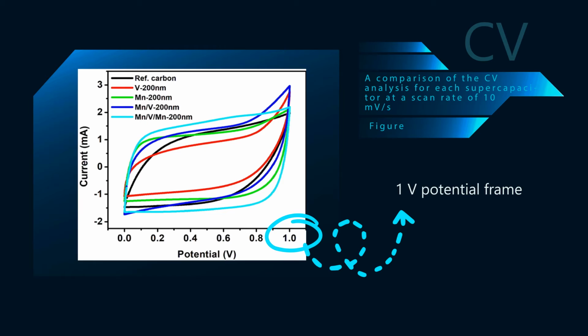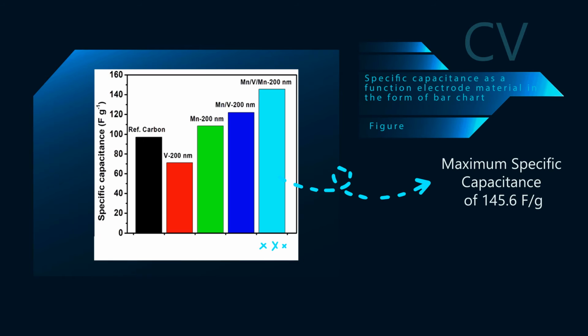In this figure, we show the cyclic voltammetry results of multiple supercapatteries analyzed in a 1 volt potential window. In this figure, we see the specific capacitance as a function of electrode material in the form of a bar chart. Clearly, we obtain the highest capacitance of 145.6 farad per gram in the multi-layered electrode of manganese, vanadium, manganese.